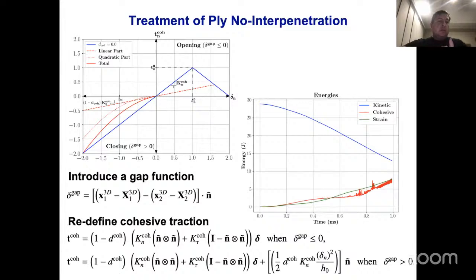And then finally, when it comes to impact and dynamic problems, supposedly there's delamination between the 2 plies. So when the plies separate, you don't want to introduce any traction. You want them to separate freely. But then when the plies move toward each other, you don't want them to interpenetrate. And so, of course, the natural choice is to use the cohesive stiffness in the normal direction to preclude the interpenetration of the plies.